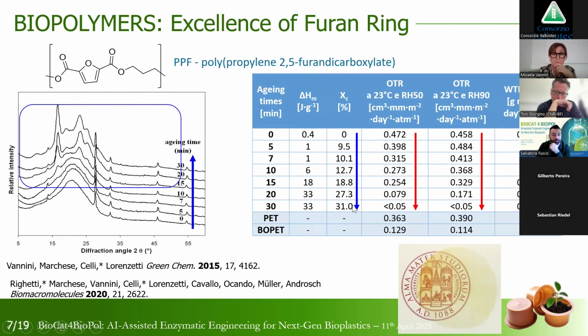In particular, PPF with 31% crystallinity provides a near total oxygen barrier, and considering the water vapor barrier, it's reduced to 1/7 compared to non-oriented PET.